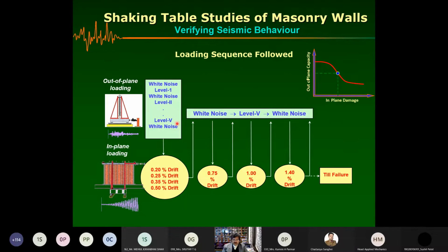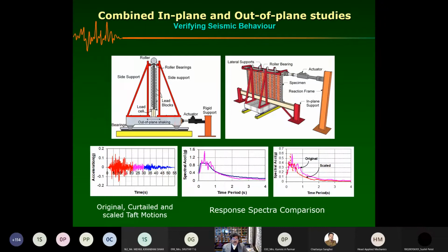So in experiments we can carry out, we can apply out-of-plane shaking. That's a more realistic simulation of your out-of-plane loads on that structure. So you can put this specimen on the shake table and shake it in out-of-plane directions. And for the in-plane, I can apply a known amount of damage. So I can apply 0.5% drift one cycle and create some damage and then run the out-of-plane tests, you see. So this is one way to utilize two different testing schemes to evaluate out-of-plane resistance of the cracked masonry.